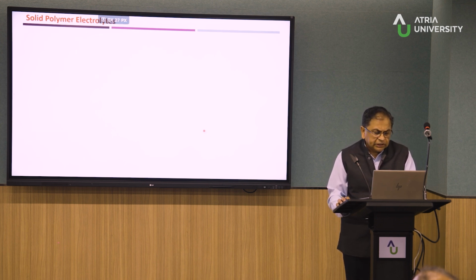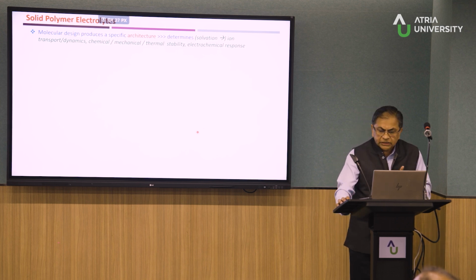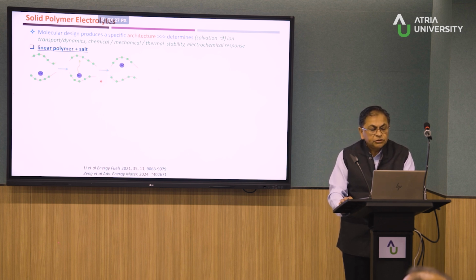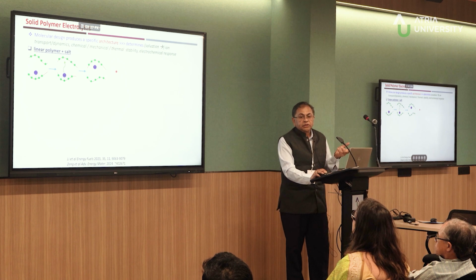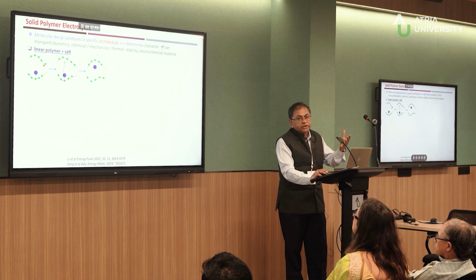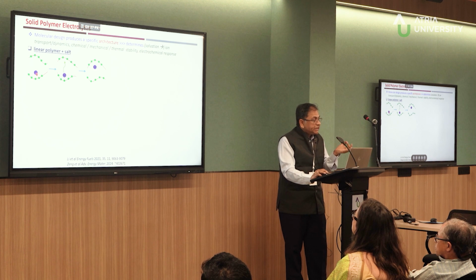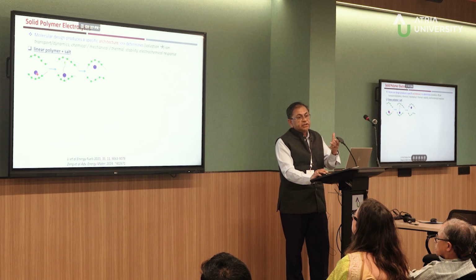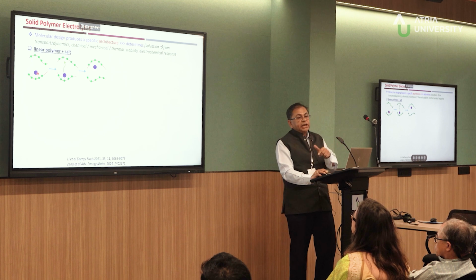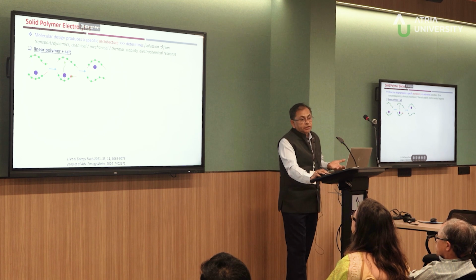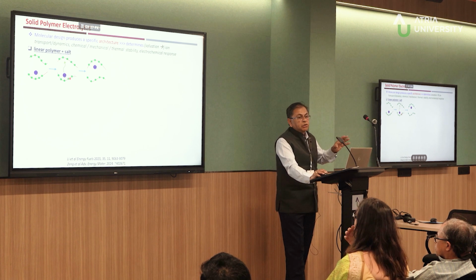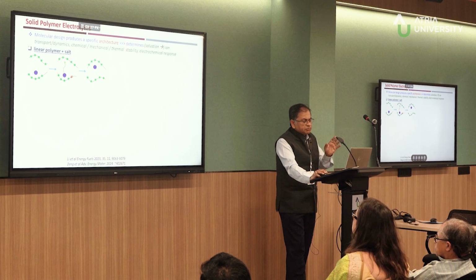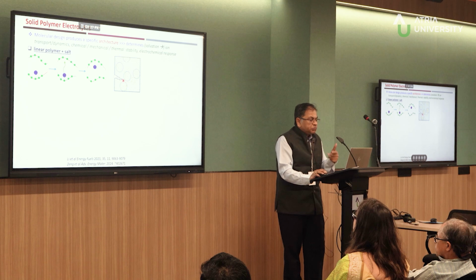So as I said, we have been working on these systems for quite some time. Now, by solid polymer electrolytes, I'm not really referring to the kind of systems which were there for a very long time. The so-called solid polymer electrolytes, where you have a very high molecular weight polymer system, and the ion of interest, which is lithium or sodium, is basically tacked to the polymer. Okay, only if there is a significant amount of mobility in the polymer will you get a significant amount of conductivity. Most of these designs early on in the 80s or early 90s used to work well only if you are very close to the melting point of the polymer. Okay, and these have very strong aging problems. With time, the membrane disintegrates. You have problems, mechanical failure and all.